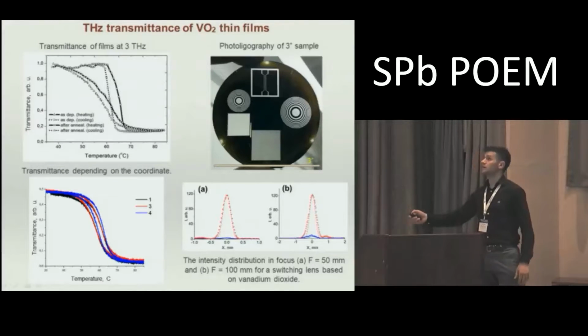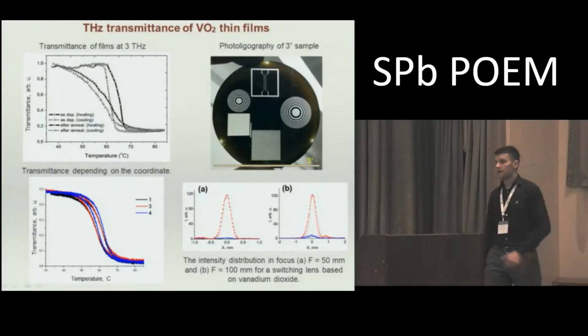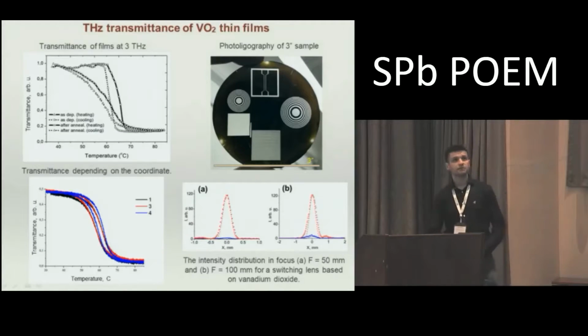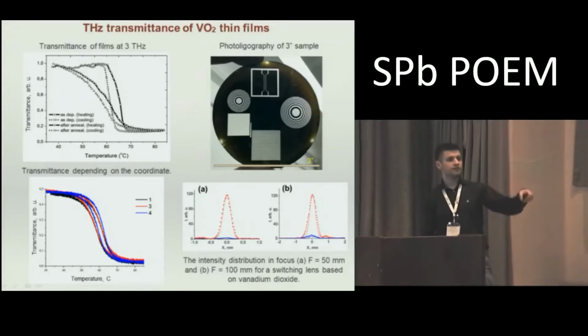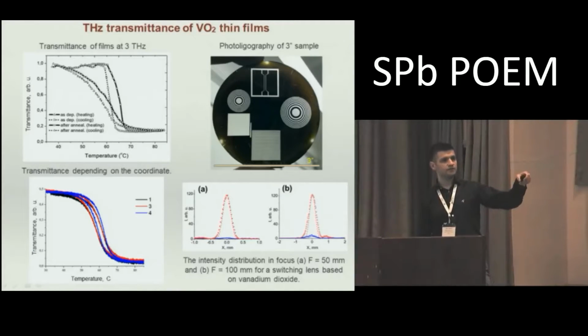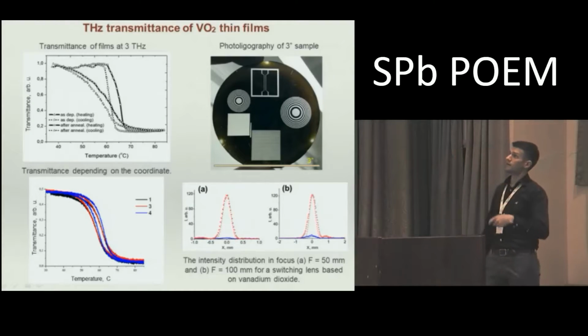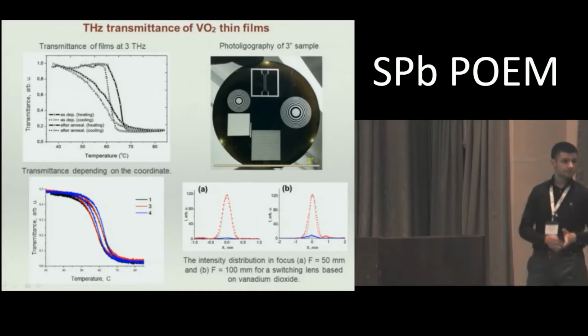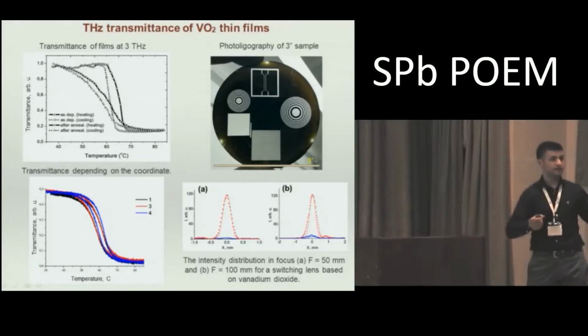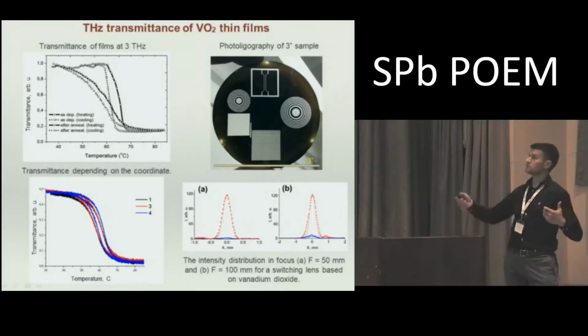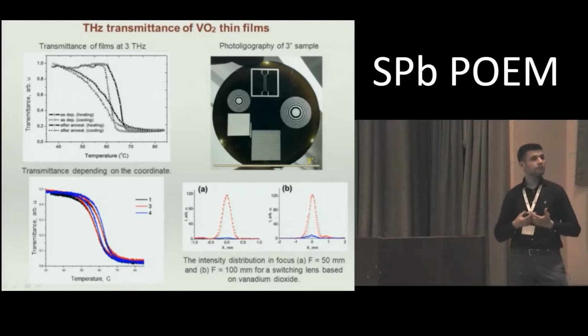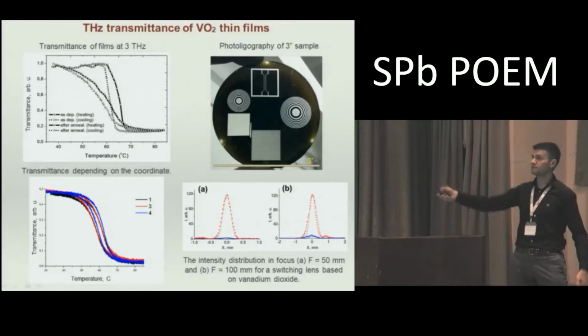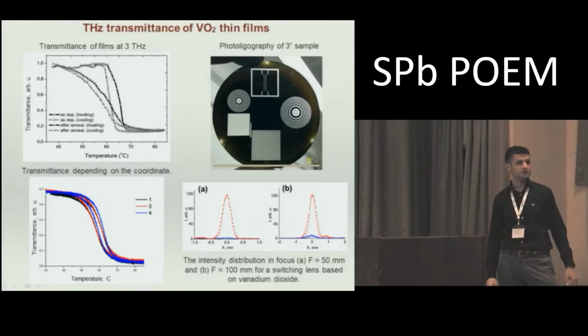Yes, it happens because in the sample without annealing, we have some oxidation phases of vanadium, not the pure vanadium dioxide, but vanadium O2 plus X. So these phases show the transition at other temperatures. So if we combine them, we will have some kind of hysteresis.